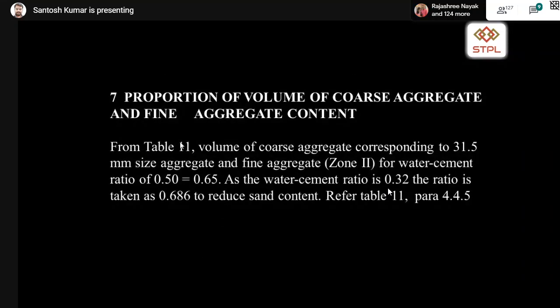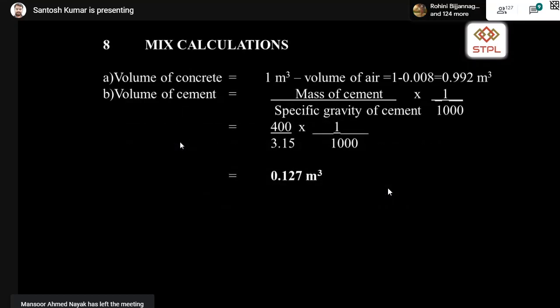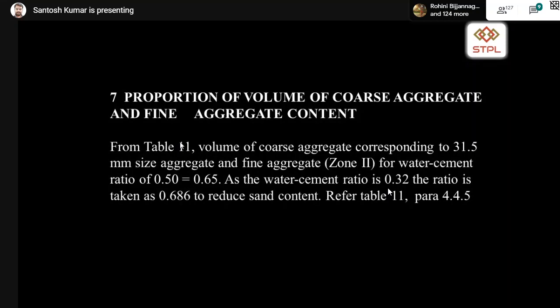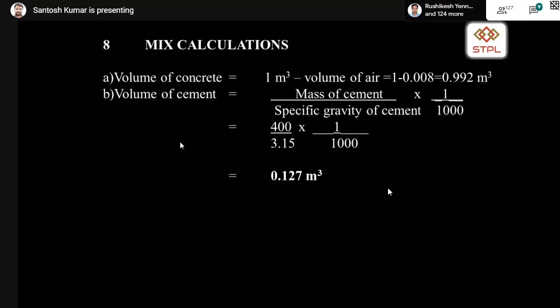So what we do is we take the volume of coarse aggregate and volume of fine aggregate. One thing I want to tell you, sir, in this design, the table number is different. Table number 11, but in that design it was table number 15, I suppose. So based on the size of the aggregate and the strength of the concrete, you have to change the tables. So in this table, we have taken accordingly the coarse aggregate proportion as 0.686 after corrections. So volume of concrete is 1, and the air content is here 0.8%.